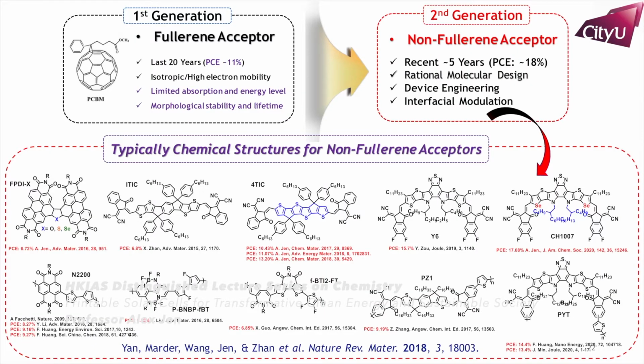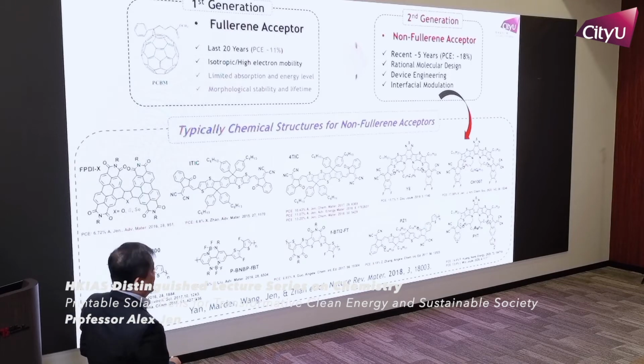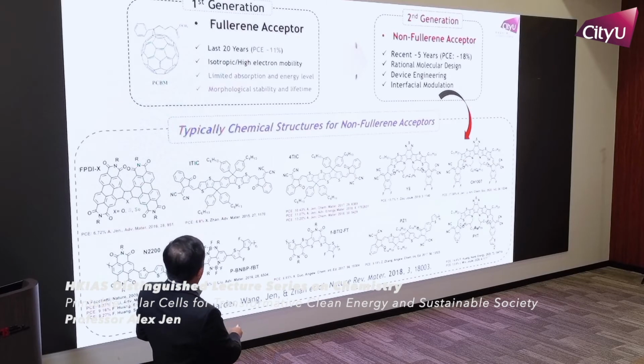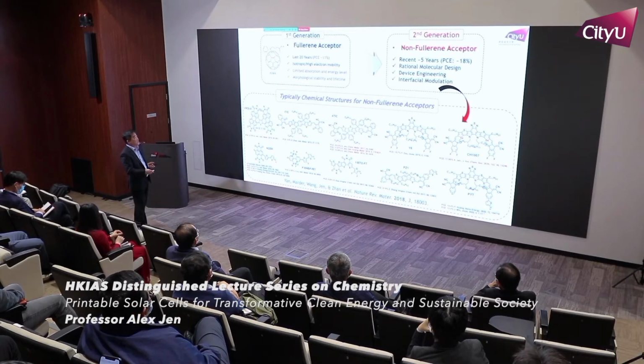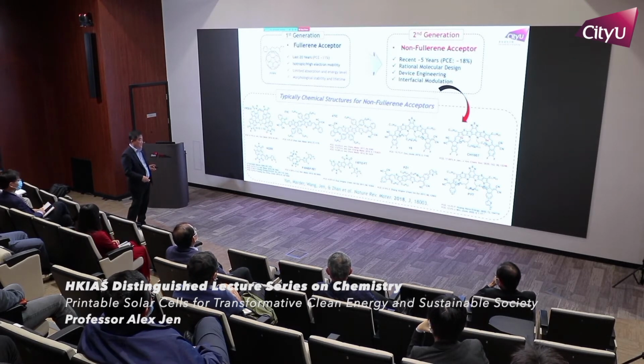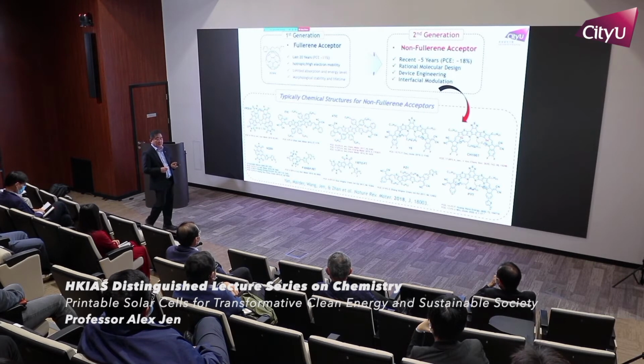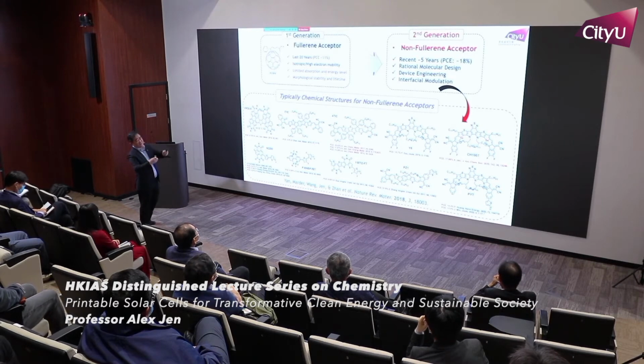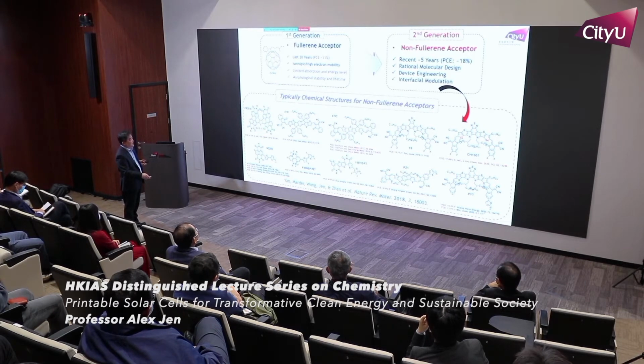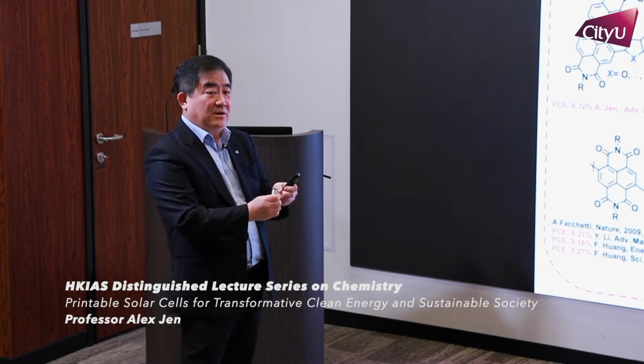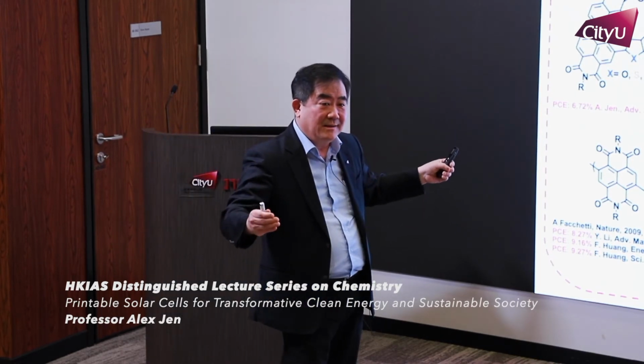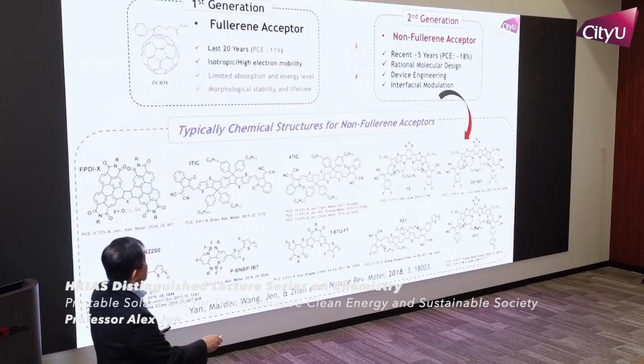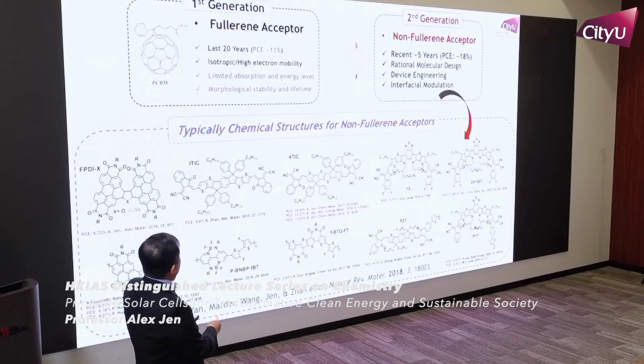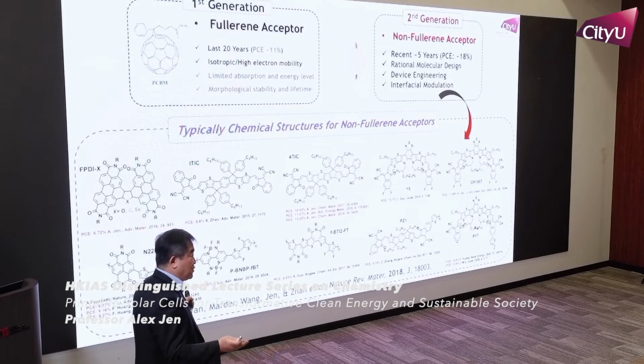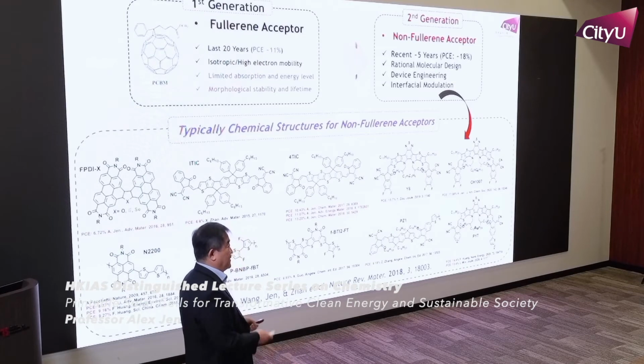So this is compared to the perovskite solar cell. The fullerene acceptor, C60, was developed and generated for more than 20 years. People put in tremendous effort, and no matter what you do, you get a PCE of around maybe 11%. And more recently, one of my co-authors, Xiaowei Zhan, also started to promote the non-fullerene acceptor, meaning not fullerene. Then, based on all the different kinds of molecular design, you can tune their absorption, their energy level, their molecular packing, all the different properties, in order to make a device. So in just a few years, it has already improved from that to 18%, with a potential to go to 20%. Okay, so this is incredible, just during the past few years.